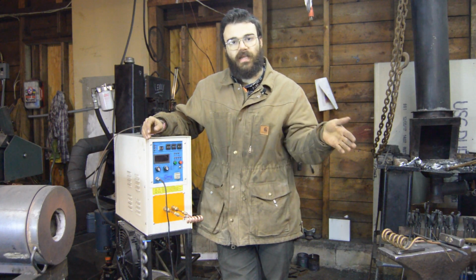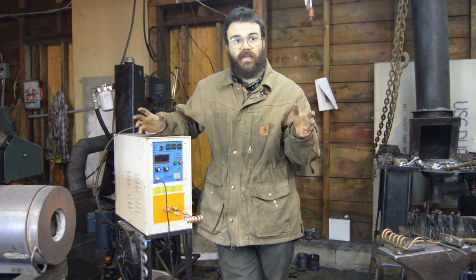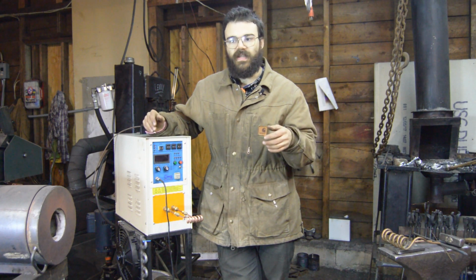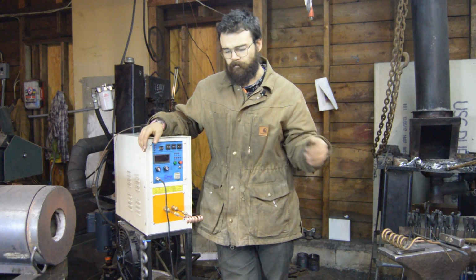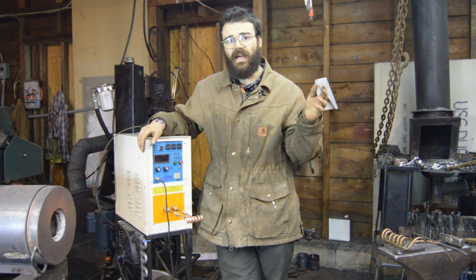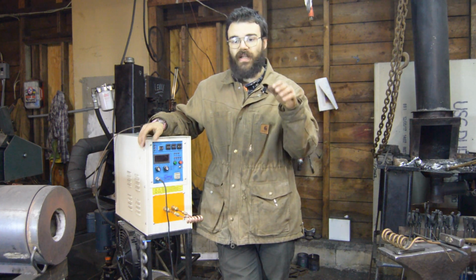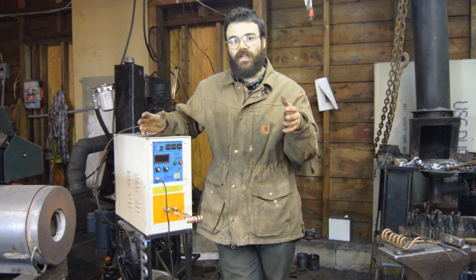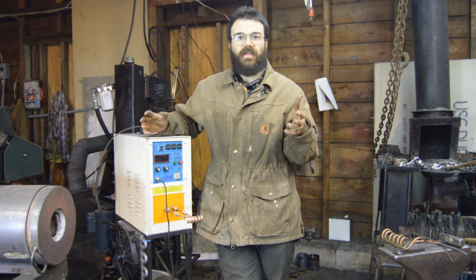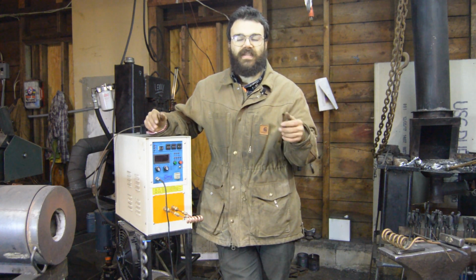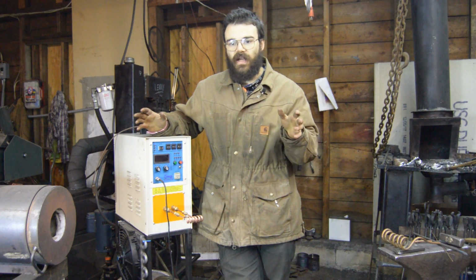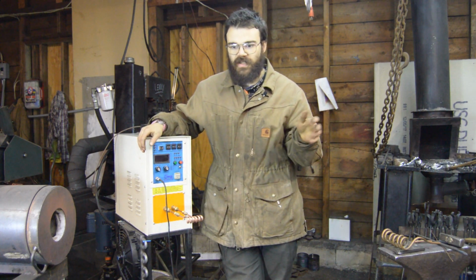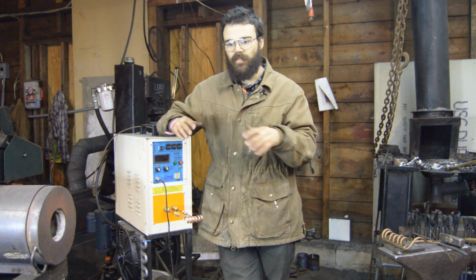Below that, below 10 kilohertz, you get into deep heating of metals, which is used a lot in induction crucibles and furnaces and things like that for smelting material. Above those frequencies, very, very high into the megahertz range, you can actually get something that's induction heating of insulating materials, so things like wood, plastic, and glass. And this is used a lot in industry for various different applications. I won't go over too much of it here, but the basics is this.